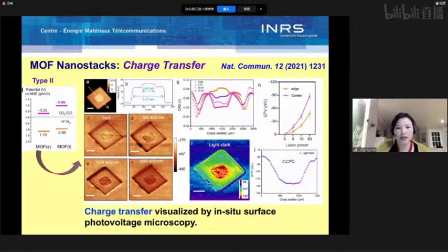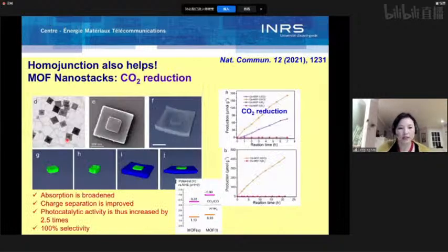So it indicates that the top nanoplate can accept photo-generated electrons transferred from the bottom nanoplate. By using this technique, we confirmed charge transfer from the bottom plate to the top plate, meaning from the larger nanoplate to the smaller nanoplate. So this is consistent with our optical data.